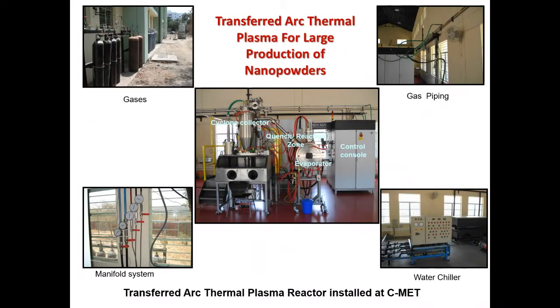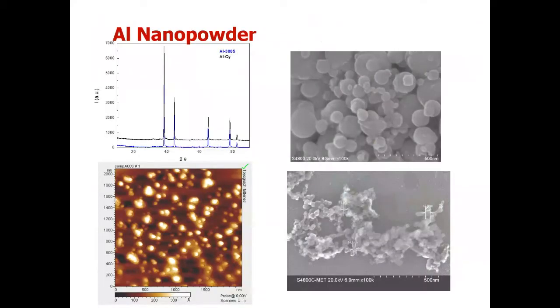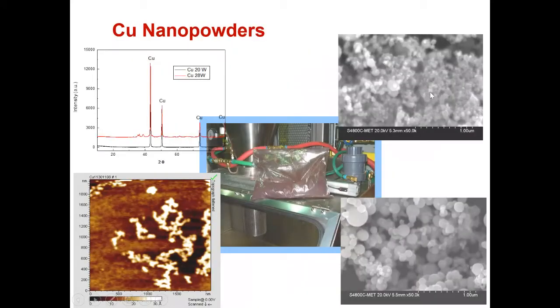So we supply to DRDO and other people the aluminum particles required as a propellant, as an oxidizer. This is the aluminum nanopowder we make. Though you see the bigger ones, they are smaller particles accumulated, giving a ball kind of structure, but they are very fragile, and we can use it for propellant applications. Copper nanoparticles of very high purity and a very small size of 10 to 20 nanometer we can also make.